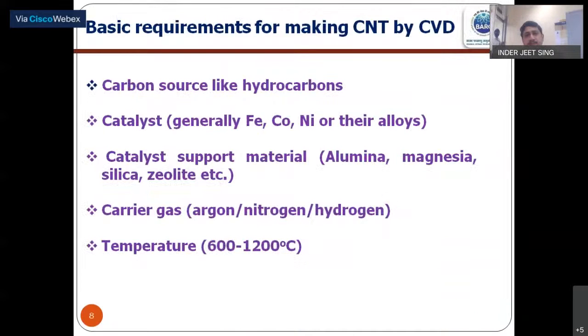Now the basic requirement for making carbon nanotube by CVD, that is chemical vapor deposition: we require a carbon source like hydrocarbon. We require a catalyst, mostly transition metal catalysts or their alloys. Catalyst support material for dispersing the nano catalyst on that so that they don't agglomerate. Then we require a carrier gas to dilute the hydrocarbon, and we require some temperature to give the required activation energy for growth of the carbon nanotube.